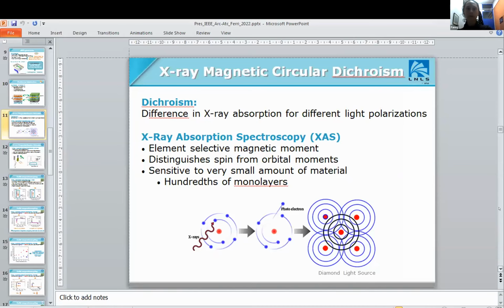The main advantage of this spectroscopy is that it's element selective of the magnetic moments. So you're able to probe exactly one element in your system. Here we wanted to know what is the behavior of the cobalt lattice and what is the behavior of the gadolinium lattice. So XAS allows us to have the behavior of both of them. It's also possible, though not so much used here, to distinguish between the spin moment and the orbital moment. And for multilayers, you don't need a large amount of material, so hundredths of monolayers. Even at some nanometer thickness, we were able to use these techniques. So this is for X-ray absorption spectroscopy.